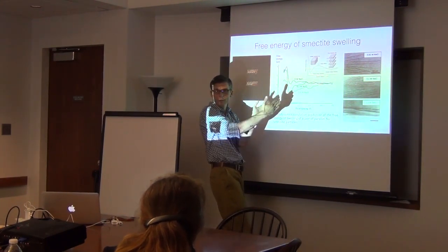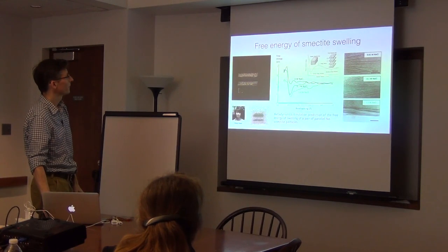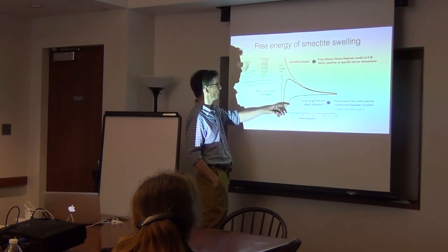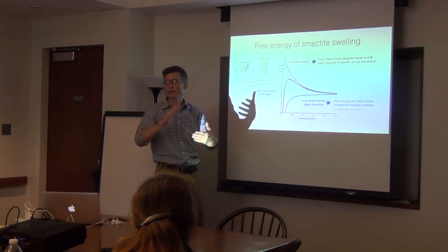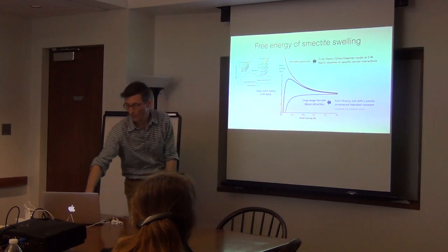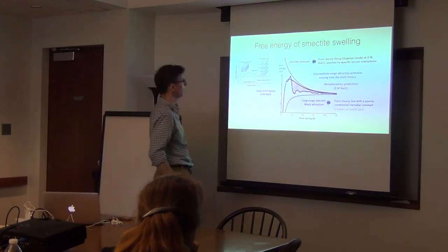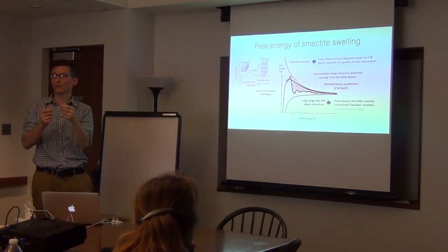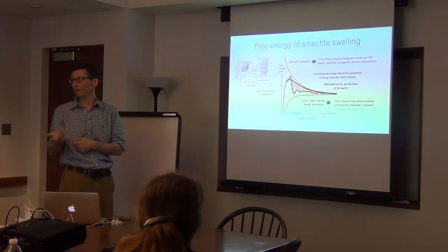From this project, we're comparing our results with theories like DLVO theory that are entirely based on long-range interactions — a long-range Coulomb repulsion and a long-range van der Waals attraction. DLVO theory predicts a free energy landscape that's quite different from what we actually get. Our hypothesis is that this discrepancy is something the mean-field theories aren't accounting for, like specific ion-ion interactions in the electrical double layer. From the molecular simulation trajectories we should be able to go in and determine exactly what that is.